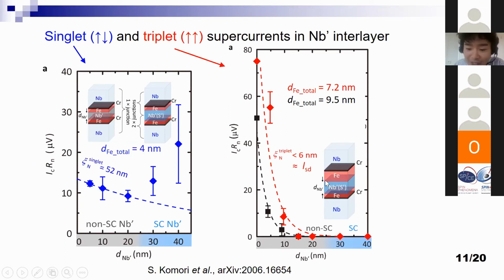So superconductivity of this interlayer can be confirmed by the RT curve, but resistance doesn't go to zero. So it doesn't create double Josephson junction behavior. This means that triplet pairs cannot mix with the singlet wave function, and they have independent superconducting condensation states. And this result is now on arXiv.